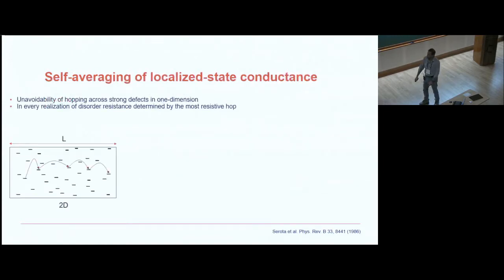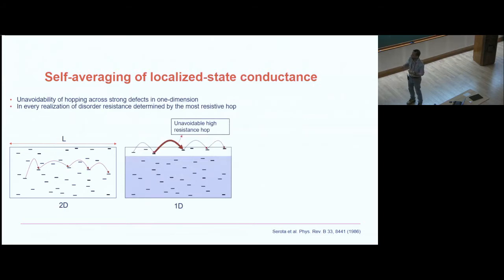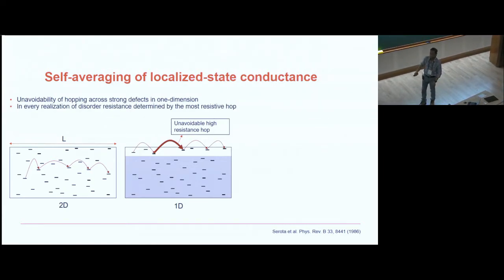So the answer is yes, there's a very interesting probe, and that's called self-averaging. And this is new. So imagine a system which is localized in 2 dimensions. What happens is the electron hops through states. If there is a large gap somewhere, the electron will bypass it and go somewhere else. I can easily bypass large areas where there are no states. Okay? So that's why in 2 dimensions you get self-averaging of electrical conductance very easily. As you make the system larger, the effect of large resistances actually decreases. In the case of 1 dimension, that is not possible.